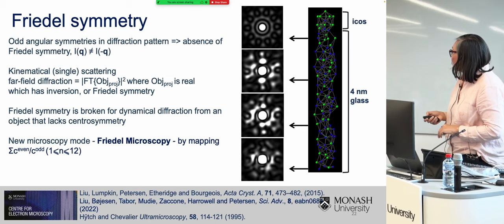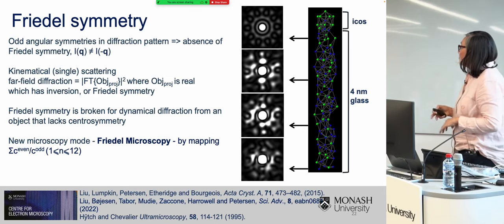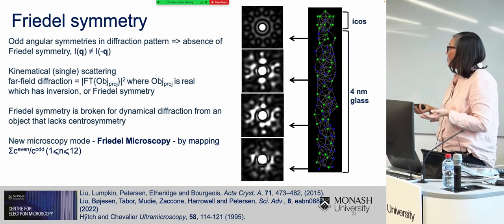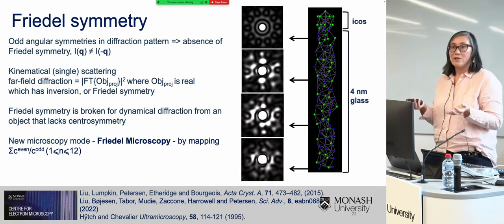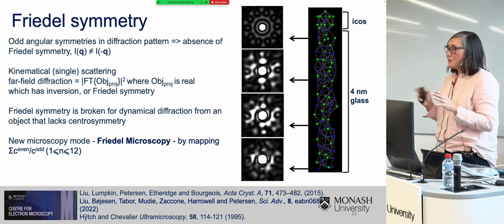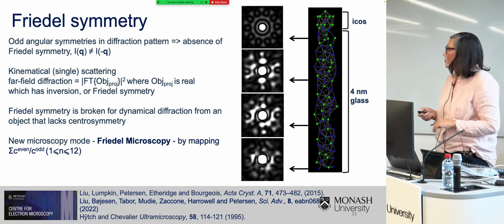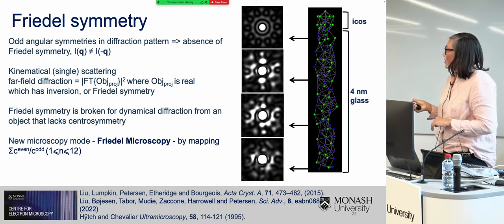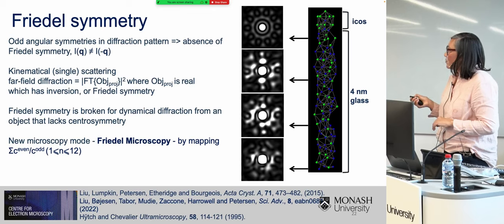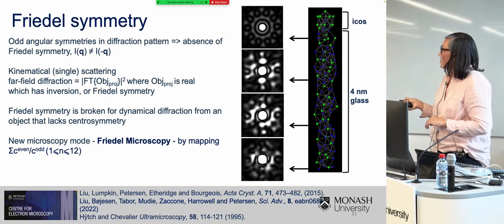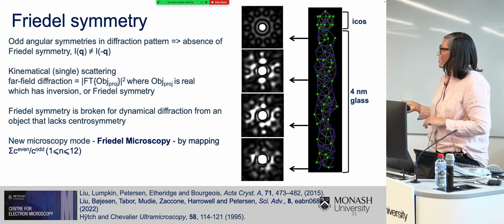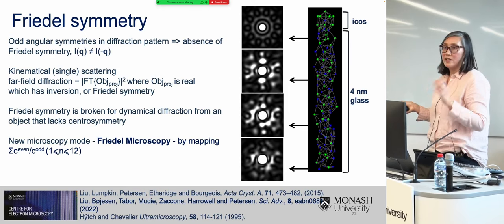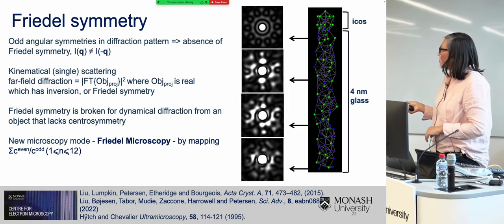Now, previously when I introduced the angular symmetry parameters that I measured from my nanodiffraction patterns, there's something that I obscured, which I will now bring to light. Each of the nanodiffraction patterns that I measured had prominent non-zero odd angular symmetries. What this means is that the Friedel symmetry was absent. So the intensity at Q in general didn't equal the intensity at minus Q.